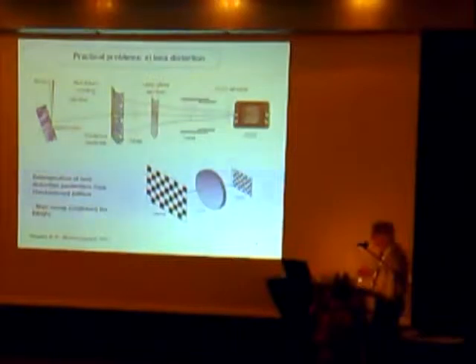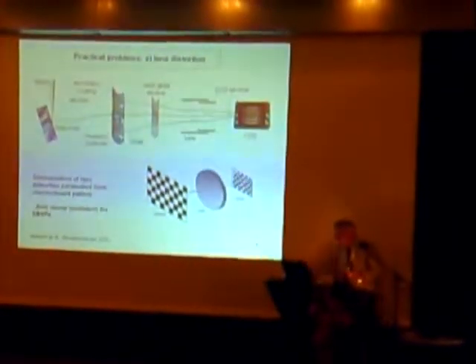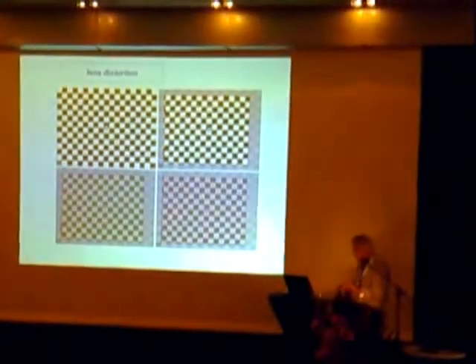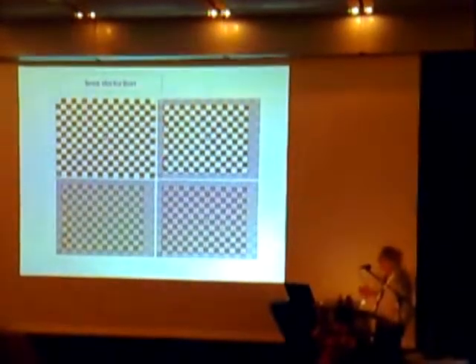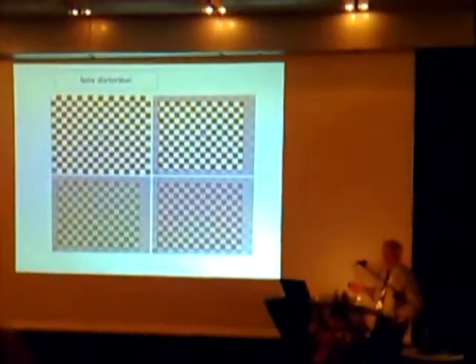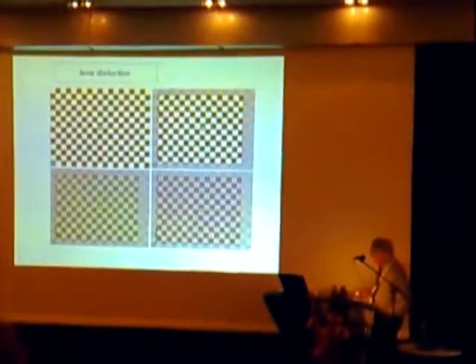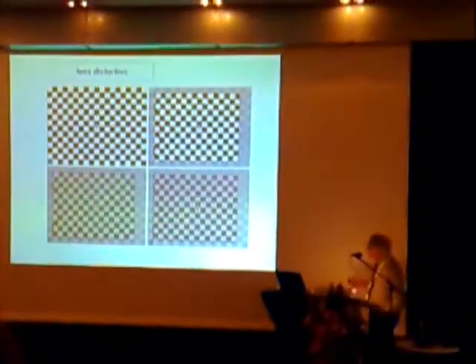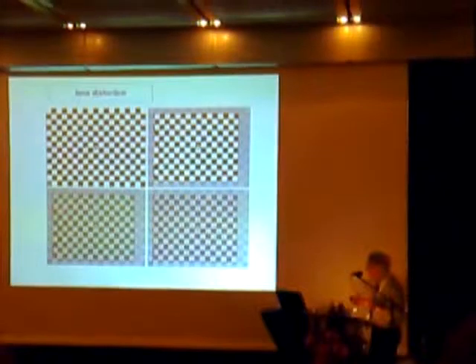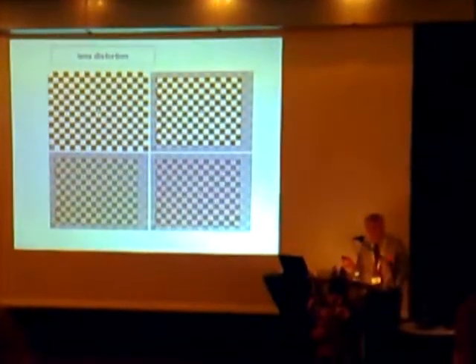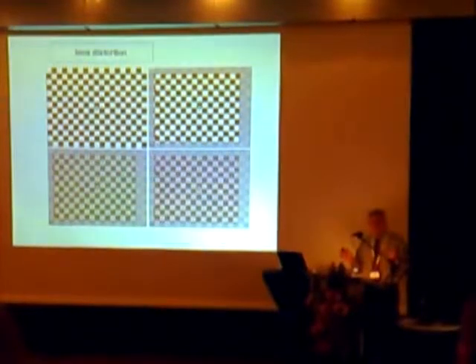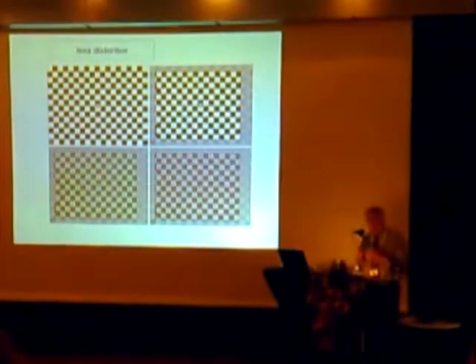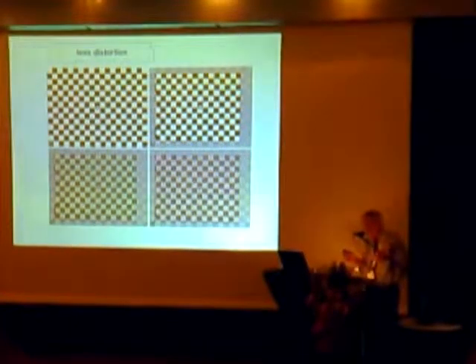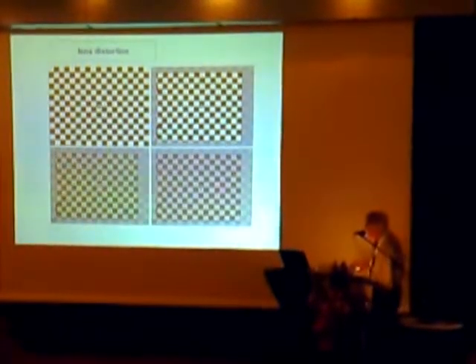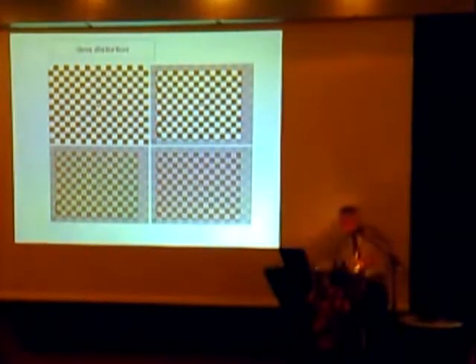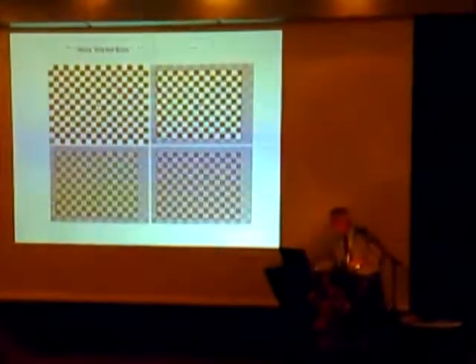And the image of this pattern is distorted. This is the checkerboard pattern, and this is what your CCD camera sees. If you look here, you can see the way that some lines are rotated and barreled. These are not major problems. They have no influence on standard EBSD, but they have influence on measuring small shifts in the pattern. And the question then is what you can do; in fact, you have to, if you like, go back to this.